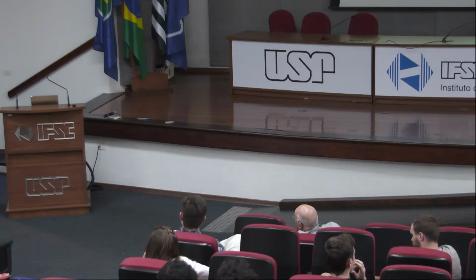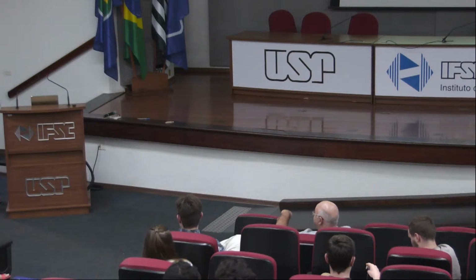It works very well. We are observing this now that we are trying to make 3D printing, and the media for printing is an organic resin. Then we have a lot of organic material, the binder, that has to be eliminated before sintering. And so that's hard. Even 1% is enough to get the sample black. And if you overheat it, it foams. It's difficult.